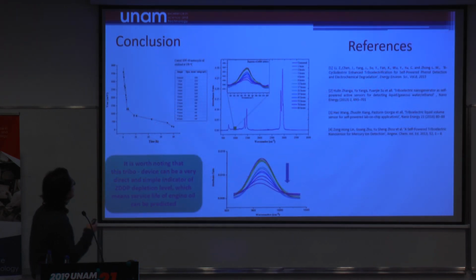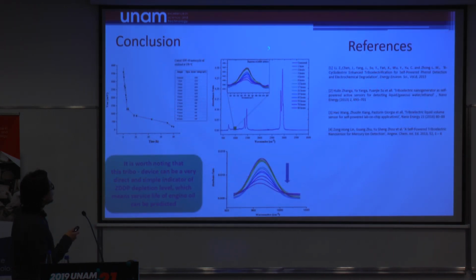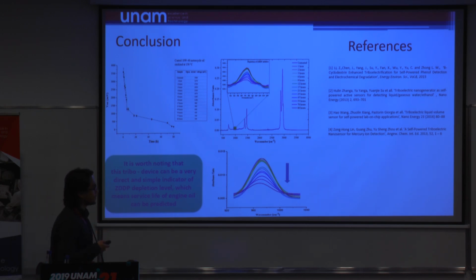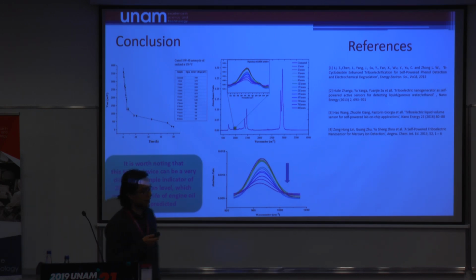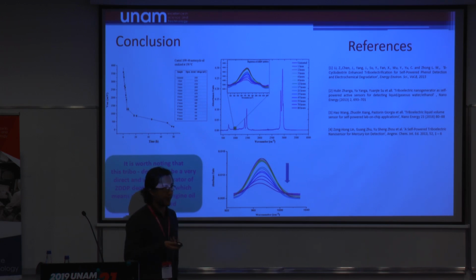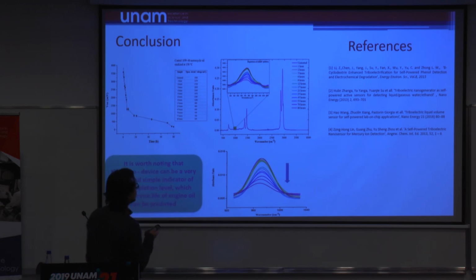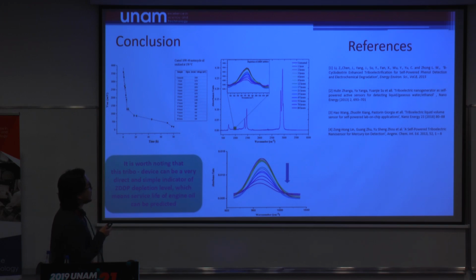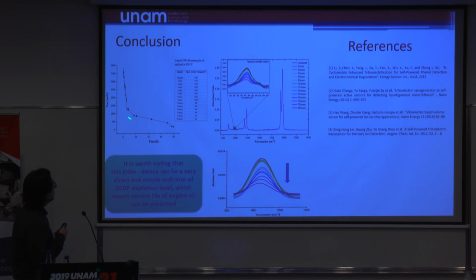So this is our overall result, and we can see the ATR characterization peak of ZDDP, zinc dialkyl dithiophosphate additive, which is a very important anti-wear additive in the engine oil industry. We can easily see that from the untreated sample to the oxidation time of 80 hours, it's completely depleted, and this output signal also decreased all the way.